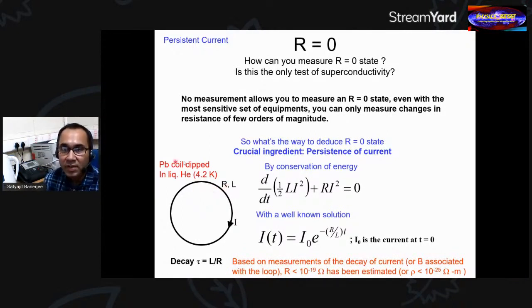So the time for which the current you have set up circulates actually depends on the resistance of the material. So what they did was take this loop of current and dip it in liquid helium, and then they studied how long it takes for the current to decay, because based on that you can find out the resistance. And experiments have shown that the decay is extremely weak. People have run this experiment for hours together and the current does not decay. The current continues to flow.